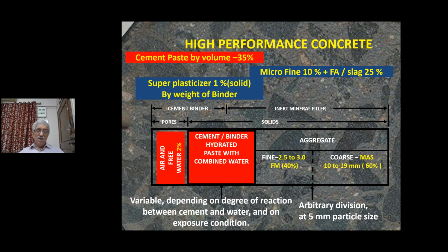Superplasticizer has to be always added by weight, not by volume. So it is very important to measure the superplasticizer, which often comes in the form of a liquid, by the solid content. One has to first inquire with the manufacturer of the plasticizer how much is the solid content in the plasticizer, and that percentage you have to add, discarding the liquid which is added for convenience of adding the plasticizer to the concrete mix.